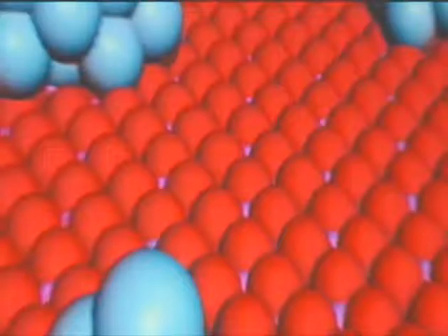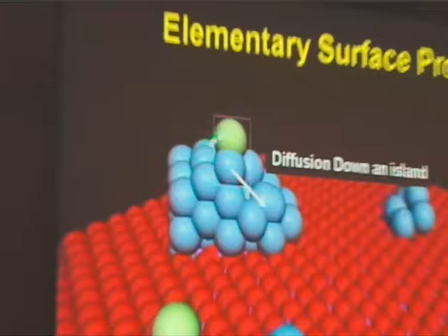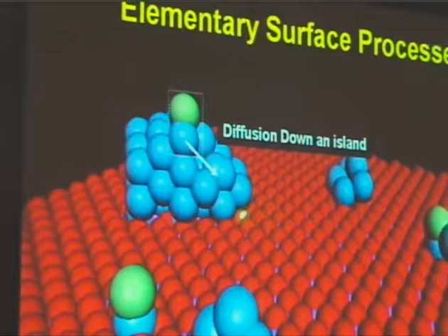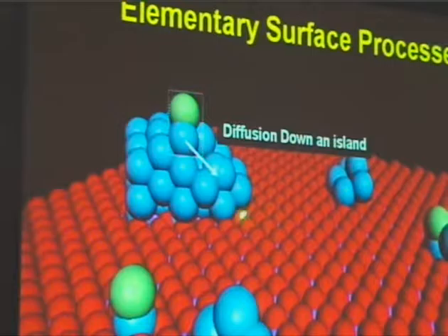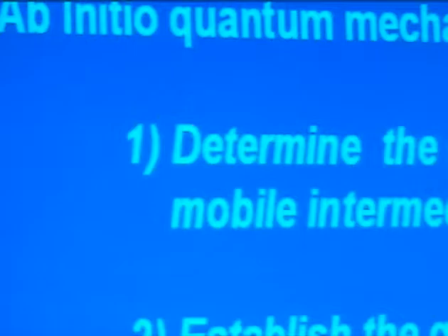We want to use theory to try to understand some of the factors that control the kinetics of these processes. We have to concern ourselves with diffusion of metal species from a larger or small particle down along the particle to the base of the metal-metal oxide interface, the detachment of some mobile species from the small particle onto the support, diffusion along the support, and then ultimately reattachment. Our approach is to use theory — periodic density functional calculations — and combine that with kinetic Monte Carlo simulations to track the dynamics and kinetics in these systems.